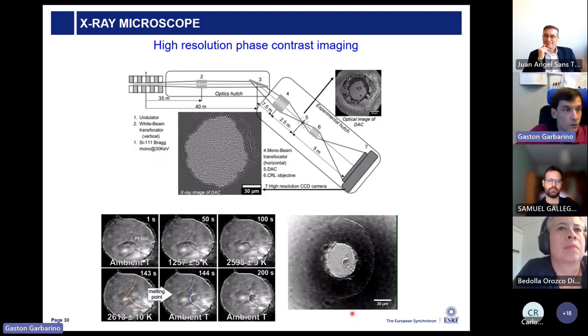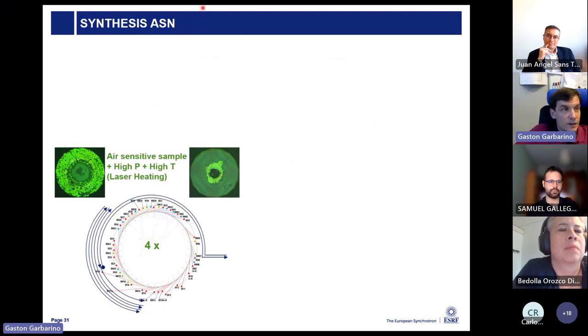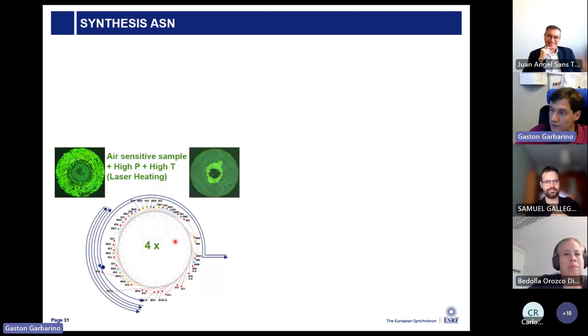Another example is the synthesis of arsenic nitride, which is a nice example because the sample was air sensitive. So we had to prepare the sample in the chemistry lab, come to the beamline to do diffraction, then move to another beamline to do laser heating and come back. We did this a certain number of times until we got a good sample. But the fact that we are able to couple all these experiments available on site allows us to develop this type of experiment.